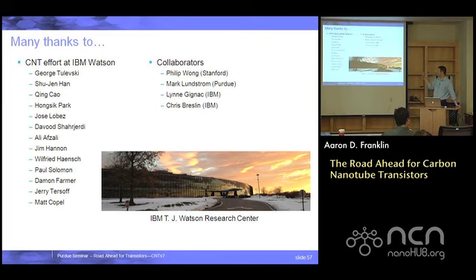So we were able to make PFETs with the gate all around simply by using an aluminum oxide gate dielectric instead of hafnium oxide. And now there's new issues. Now we have a spacer that is not doped, right? And there's a whole discussion about that. But it does still have a leaning towards hole injection based upon the contacts.